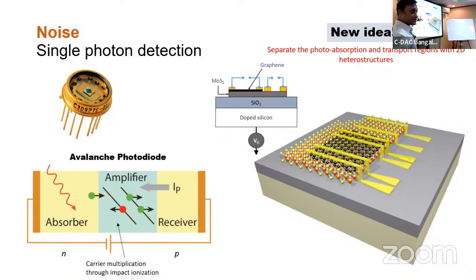So you have molybdenum disulfide, which is a semiconductor, and I put a layer of graphene on top by using the technique that I showed you earlier. Now what happens here is that when I shine light, the light comes and hits the semiconductor. It creates an electron and hole, but the electron now comes out of the semiconductor and goes into graphene and gets physically separated, because I'm measuring the resistance of the graphene. So the current flows in graphene, but the generation of charge happens in the semiconductor.